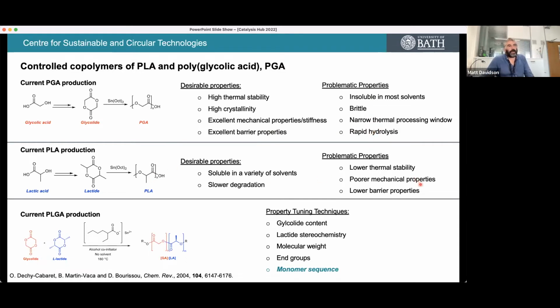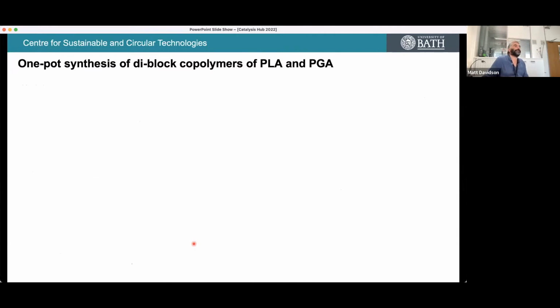We've already talked about PLA and some of the problematic properties, but also the barrier properties of PLA are not great. The copolymer of polyglycolide and polylactide, or polyglycolic acid and polylactic acid, has been known for a very long time. It's used in biomedical applications. But again, typically it's made with a tin catalyst, and what you want for these biomedical applications is a polymer with random monomers along the polymer chain. What we're interested in is seeing what happens if we can, in a relatively facile way, using catalytic control, make some more controlled polymers.